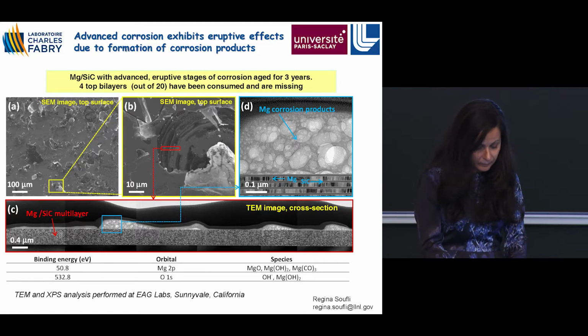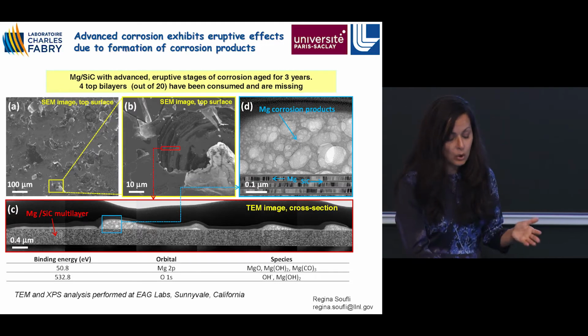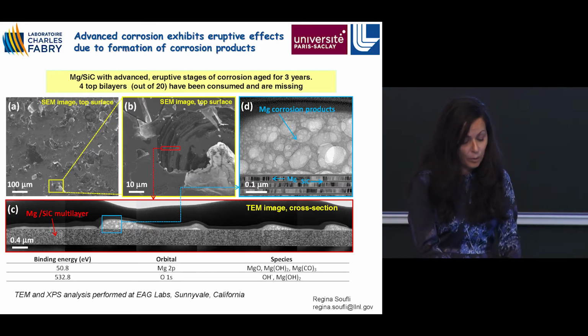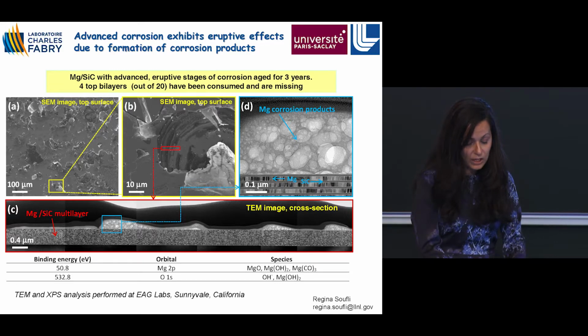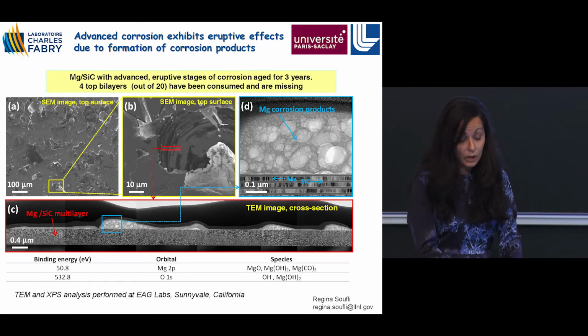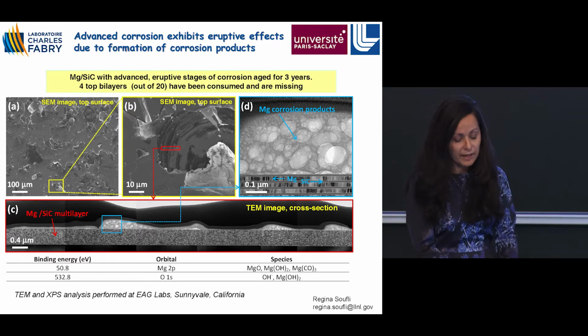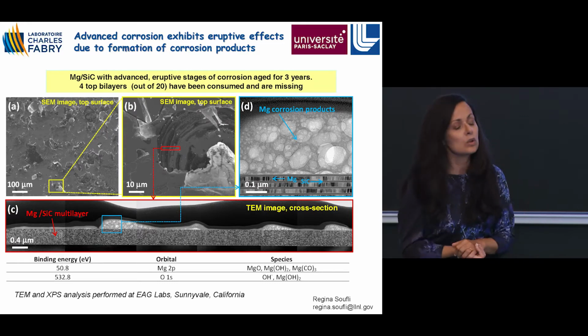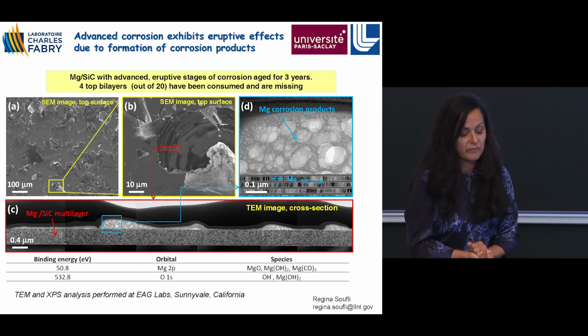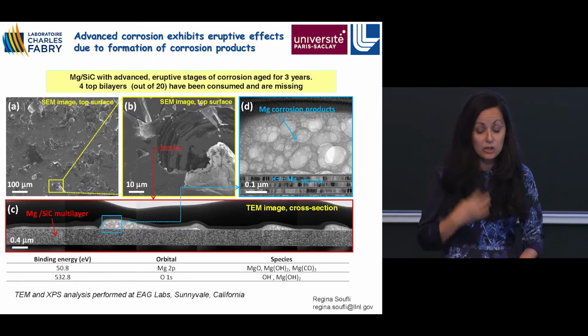Interestingly, we notice that there are 4 layers, bilayers, that have been completely consumed by corrosion and are missing from the top. You can see here the corrosion products forming, which we analyzed with X-ray photoelectron spectroscopy, and we determined that they are brucite and hydromagnesite. They're basically corrosion products of magnesium. And because these corrosion products come with volume expansion, you have these eruptive effects, basically the multilayer coating almost exploding and being destroyed.